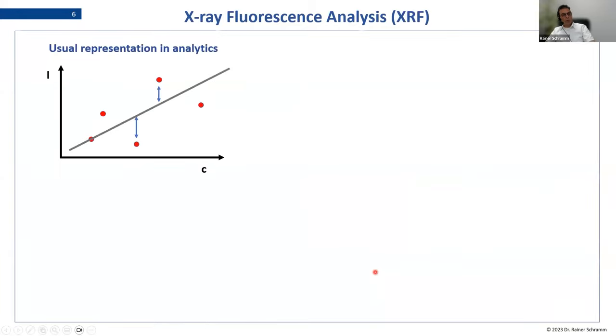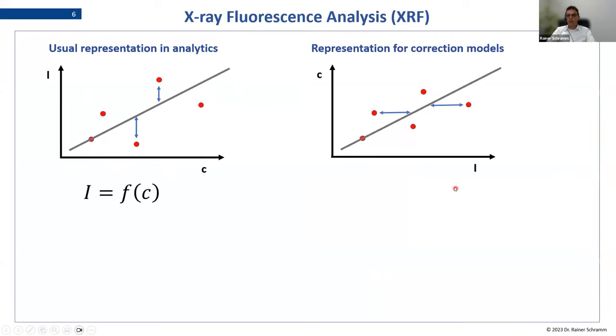Okay, so the first way we would do a calibration in analytical chemistry is that we use the x-axis for concentration and the y-axis for intensity. We put our measuring data there, and with a linear regression we try to fit a line into our cloud of points. But in X-ray, we already have one difference. We use a different presentation, so the intensity and the concentrations are exchanged. We use the intensity on the x-axis and the concentration on the y-axis, and then make our linear fit. This is because all the models we are using work on the basis of this presentation.